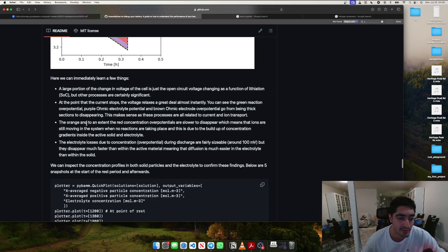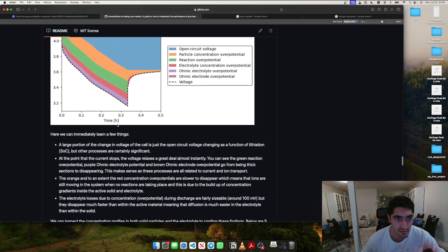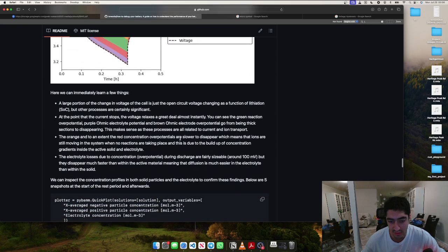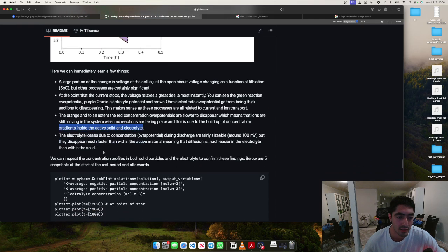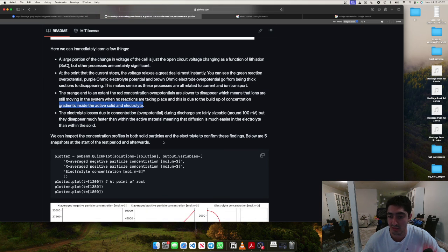The orange and, to an extent, the red concentration overpotentials are slow to disappear, which means that ions are still moving in the system when no reactions are taking place, and this is due to build-up of concentration gradients inside the active solid and electrolyte. The electrolyte losses due to concentration overpotential during discharge are fairly sizable, around 100 millivolts, but they disappear much faster than within the active material, meaning that diffusion is much easier in the electrolyte than within the solid.